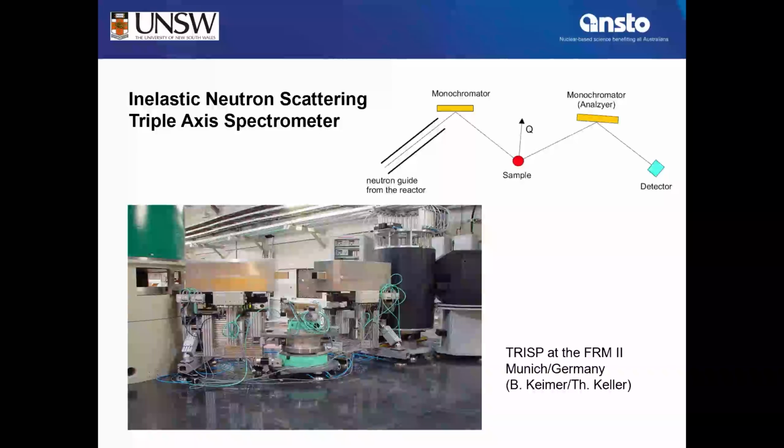The spin flipper sounds super complicated, but actually it's really just a high frequency electromagnetic field, and to initialize that, to calibrate that, we do that directly live in action at the neutron beam. So we simply detect the spin-up component and the spin-down component separately and tune the magnetic field to achieve a maximum in both. That alignment sounds super complicated, but in the end, it's a thing of 10, 15 minutes to record that. So that's polarized neutrons.